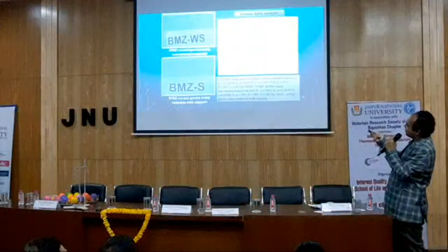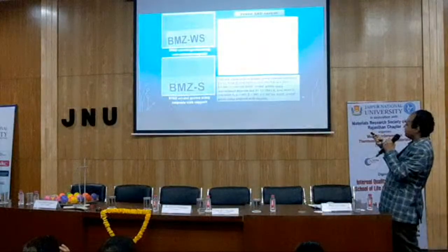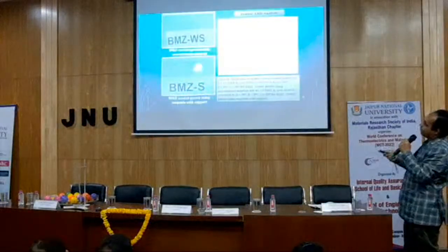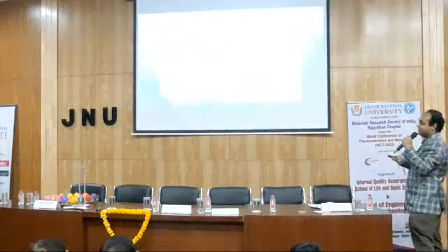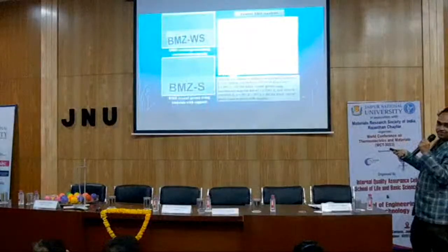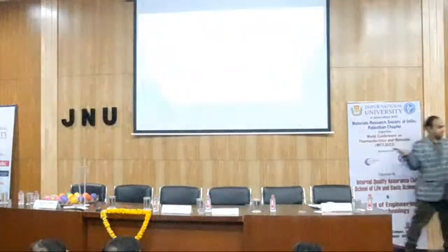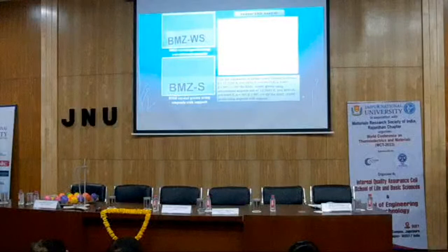If you see, everything is in phase. It is in phase, beautifully. We have confirmed with the JCPDS. Benzimidazole is a well-known organic material, and we have grown it. And this is with support. Looking at the figure we cannot see a difference, but after assessing through sophisticated techniques like high resolution X-ray diffraction, we observed a drastic change in the quality of the crystal grown using the modified procedure.